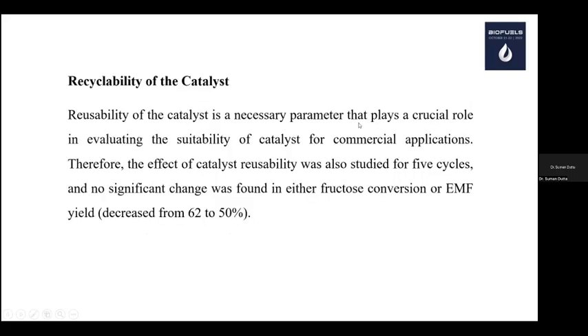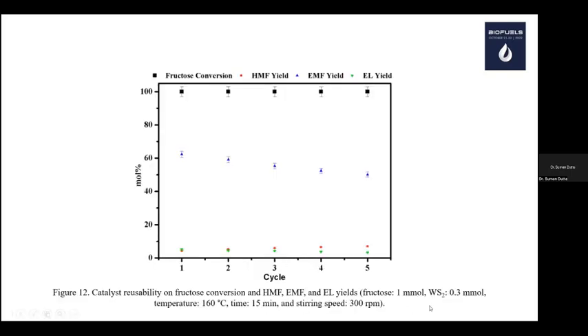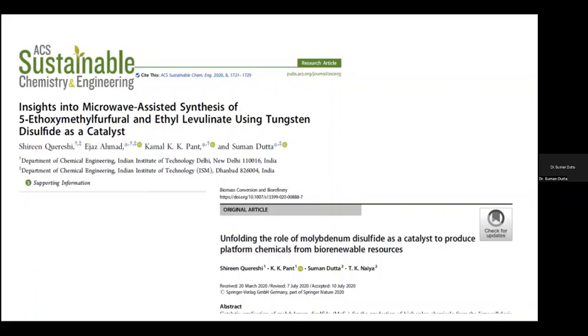We checked the recyclability of the catalyst, which is an important parameter. If a heterogeneous catalyst is not recyclable, it increases production cost. We performed five cycle experiments and found that conversion remains almost the same, and EMF and HMF yields show no significant decrease even after five cycles. This catalyst can be used for at least five cycles without any change in catalytic activity.